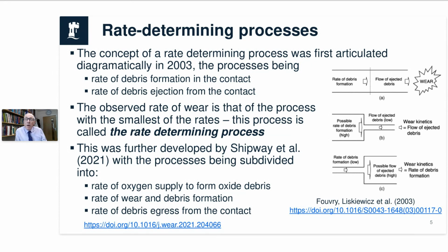It says in broad terms, if there are numerous processes that all need to happen for something to happen, in this case wear to occur within fretting, then the overall process will happen at the slowest of the rates. You think of a flow in series as they have shown it in the diagram here on the right-hand side. They talked about the rate of debris formation and the rate of debris ejection. And they said the critical word within their diagram is possible. In the second line down, it talks about the possible rate of debris formation. Sure, the debris could form quite quickly, but in reality, in the case that they're showing here, the flow of debris out of the contact was really quite limited, and therefore the overall kinetics were those of the flow of debris out of the contact. So a really nice understanding there.